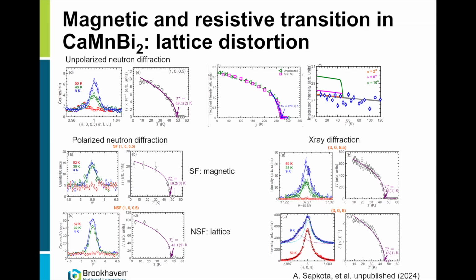But in addition to that, X-ray diffraction also shows a strain. You see the in-plane Bragg peak, H08. It shows splitting. You see, this is high temperature, single nice peak; at 9 Kelvin there is a splitting of this peak, which means that the A and B lattice parameters become unequal. So there is an orthorhombic distortion in plane. So there are two evidences in this X-ray diffraction for this orthorhombic zigzag distortion.